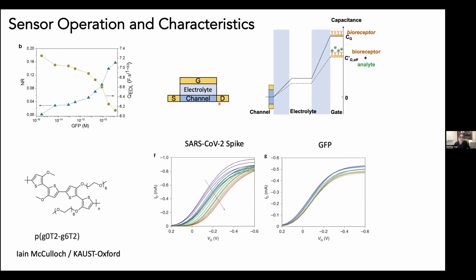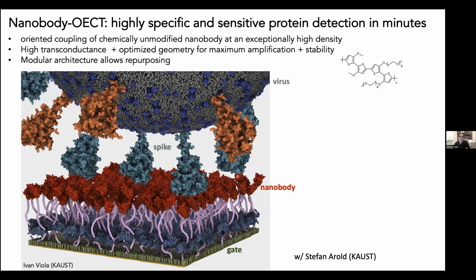Now I'm showing you what is happening to the device that we functionalize with a nanobody that is expressed for SARS-CoV-2 spike protein, that's the coronavirus, and the spike protein of the coronavirus. So this is the device characteristics, drain current that we are measuring as a function of gate voltage that we apply. As you see, as the gate electrode is exposed to solutions that contain more and more of the spike protein, you see a drastic change in the transfer characteristics of the device, the current that you measure from the device. If you expose the same gate electrode to green fluorescent protein of equivalent concentrations as the spike protein, the changes that you see are very nominal, minimum. This shows the selectivity of the sensor, and its very high sensitivity.